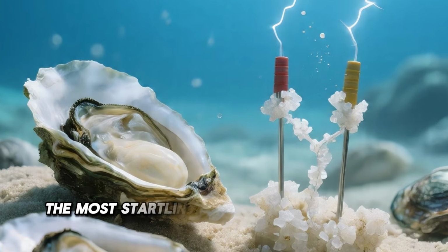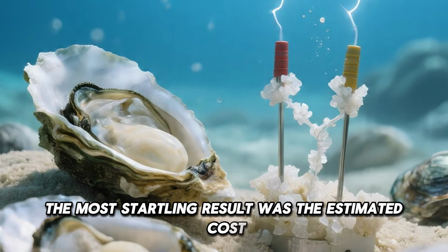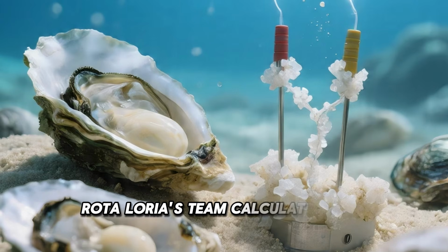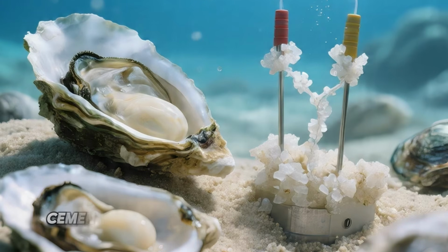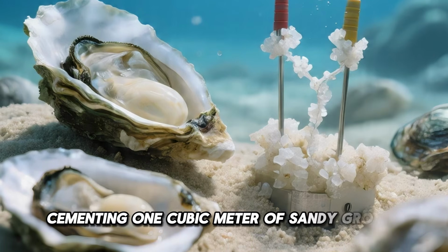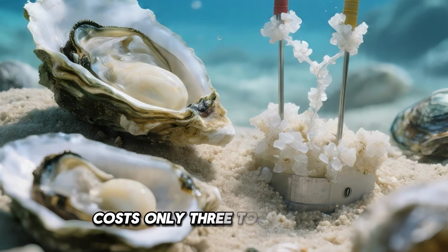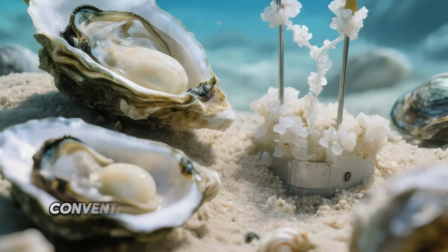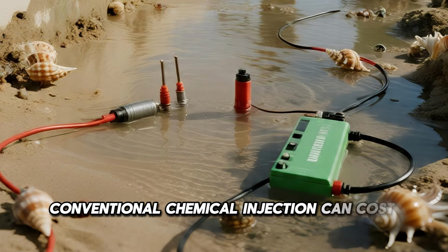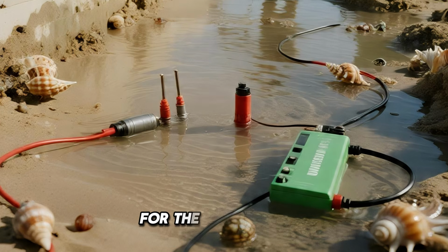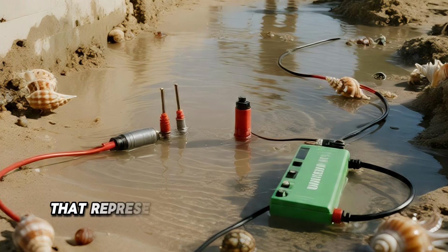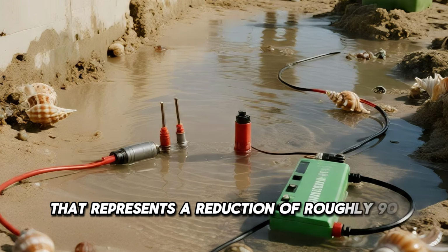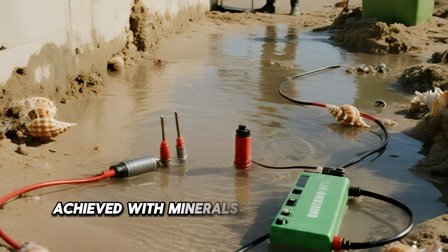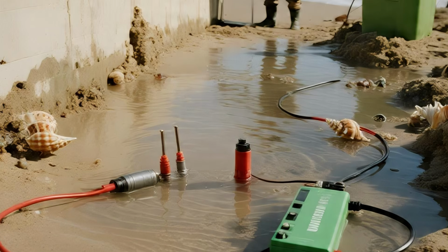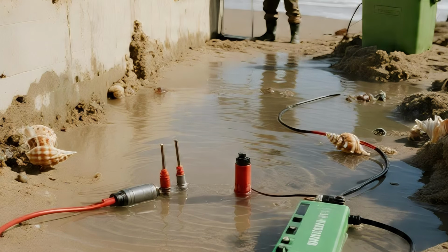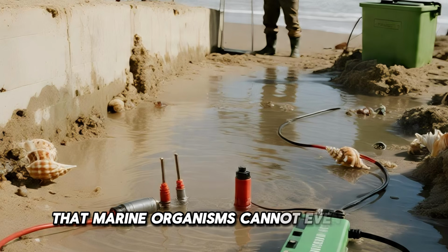The most startling result was the estimated cost. Rota Loria's team calculated that electrically cementing 1 cubic meter of sandy ground costs only $3 to $6. Conventional chemical injection can cost as much as $70 for the same volume. That represents a reduction of roughly 90%, achieved with minerals already present in seawater and with voltage so mild that marine organisms cannot even feel it.